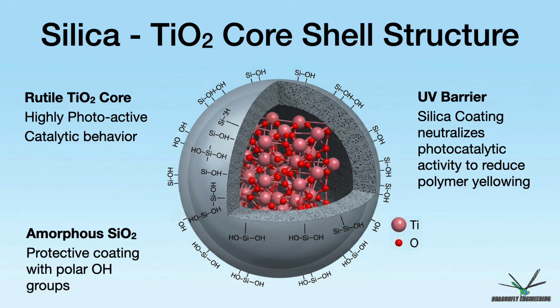Tioxide is highly photocatalytic, which is not super ideal for plastics. With a band gap of 3 eV, the tioxide crystal will absorb UV, which has more energy than visible spectra, and then in turn generate free electrons. If there's no encapsulation, these excited electrons react with ambient moisture and oxygen to create highly aggressive free radicals, which can degrade organic material, specifically plastics. With the silica encapsulation in place, photogenerated electrons stay trapped inside the tioxide core and are blocked from interacting with the base resin.